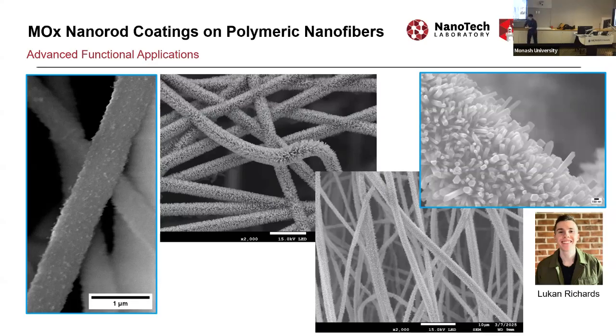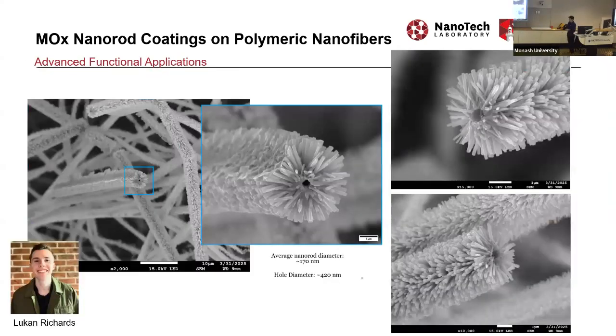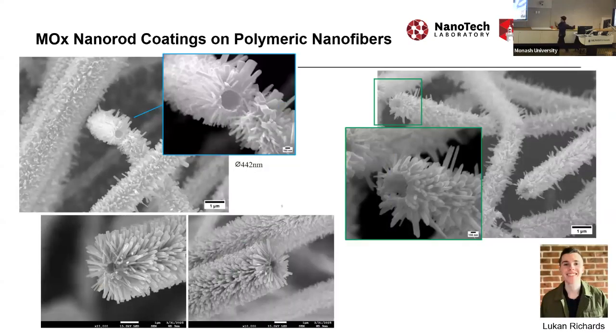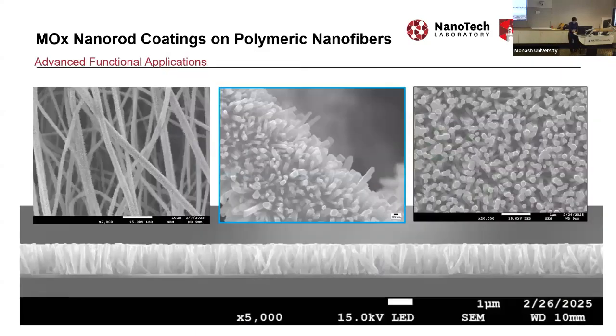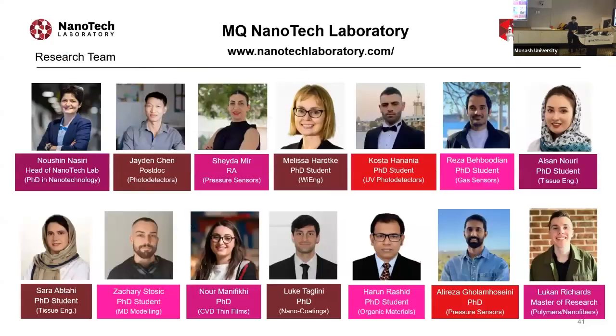In some cases, he kept the fiber, but in other cases, he put the fibers in the oven. He decomposed them and got rid of the polymer inside. Then by changing the size of the polymer, he created this hollow structure, which we are working on with a collaborator on drug delivery. He can manipulate the size of the fiber, make it bigger, make it smaller. You can also change how the nanorods grow on the surface. And that is on the fiber, but you can actually do the seeding on top of any deposited film. There is a tiny film deposited here on the substrate. He does the seeding on top of that, and then grows the nanorods on top of that.